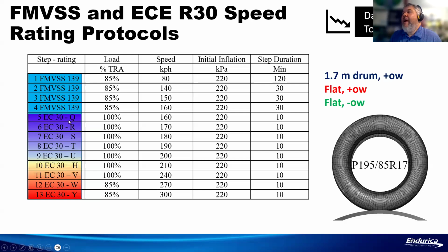And now if the tire passes this, it's legal to sell the tire. But this does not get you a speed rating. To get a speed rating, you've got to now put the load at 100% of rated load and then keep ramping up the speed. They run these in steps of 10 minutes. So they'll run the speed for 10 minutes. If the tire hasn't failed, they bump it up to this one.